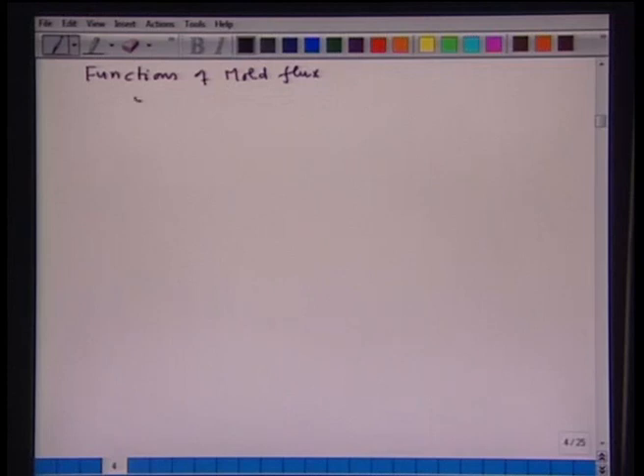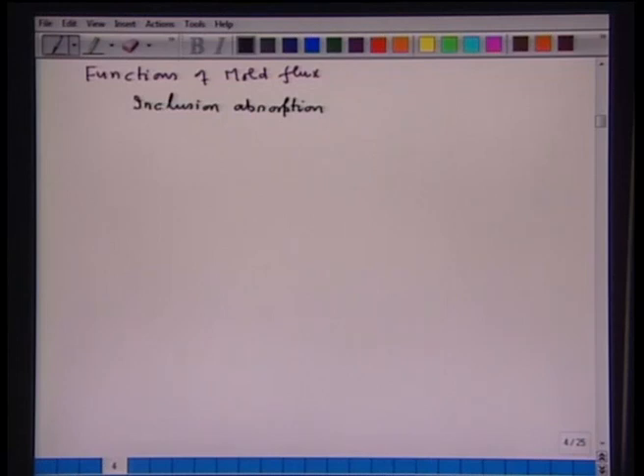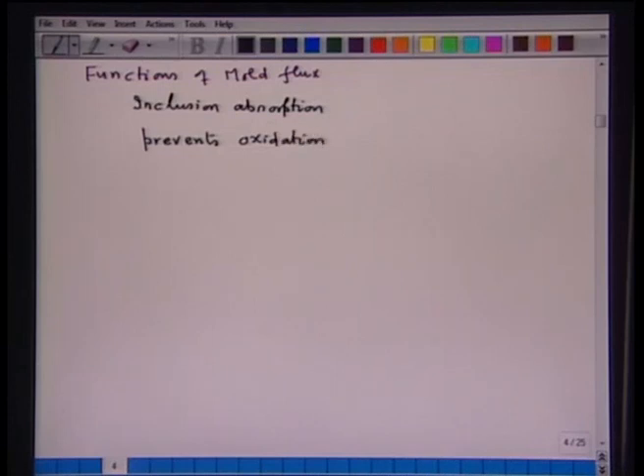First, it helps in inclusion absorption, because no sooner mold flux is added on the top of the liquid steel, it melts and due to stirring or due to floating of the inclusion, it can be very well absorbed by the flux, which is molten and kept on the top of the liquid steel. It also prevents oxidation — because all the time, the top of the liquid steel in the mold is covered by a slag. Therefore, the contact between atmosphere and the liquid steel is eliminated.